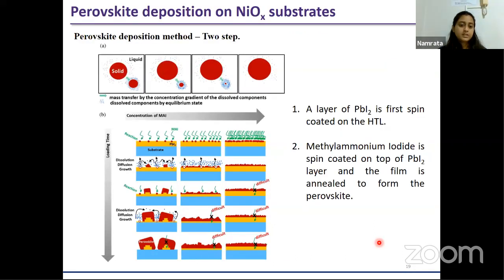So from the first study, it was clear to us that the perovskite film has a major effect from the underlayer. And to explore it more, what we did is we adopted another technique, another deposition method to make the perovskite film. So in the first study, where we were using the one-step deposition method, where we just have one solution, in the next step, we used a two-step deposition method.